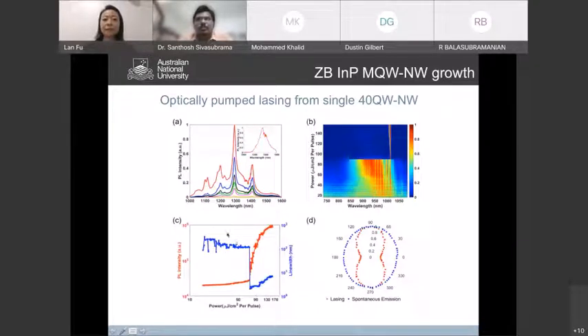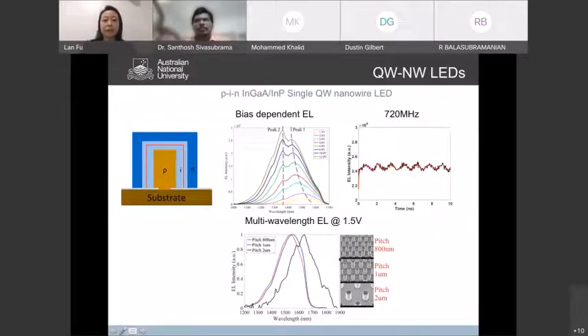Those nanowires are also able to lase. If we pump them hard, we can see very nice lasing achieved at 1.3 micron from those 40 quantum well nanowires. We further wanted to see whether we can make those nanowires into array LEDs again. This time, we created a nanowire array on the same substrate with different pitch sizes. Because of the different nanowire pitch, we have different growth rates of the quantum wells. Thereby, we're able to create quantum wells with different wavelengths, as you can see from here.